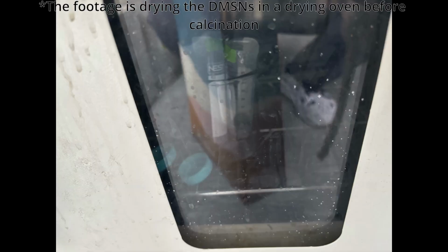The entire washing process took me almost 2 hours, and the wet DMSNs are then sent into a muffle furnace for calcination at 550 degrees C for 6 hours. This step serves to burn away all surfactants that remain trapped within the nanoparticles, generating an empty spherical shell composed of entirely pure silicon dioxide, without other nonmetal impurities. The calcined powder, DMSNs-raw, appears snow white and is a perfect catalyst support material.